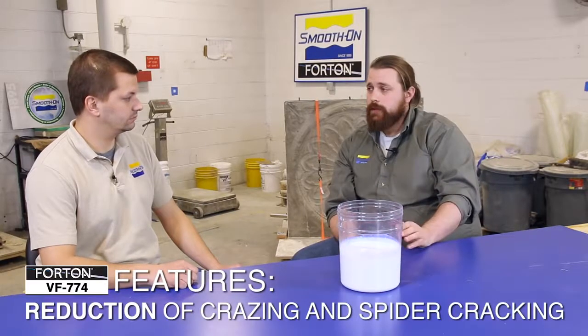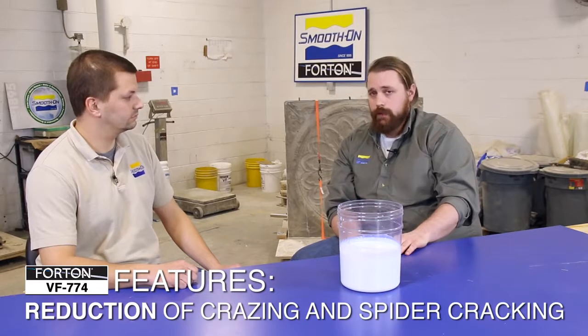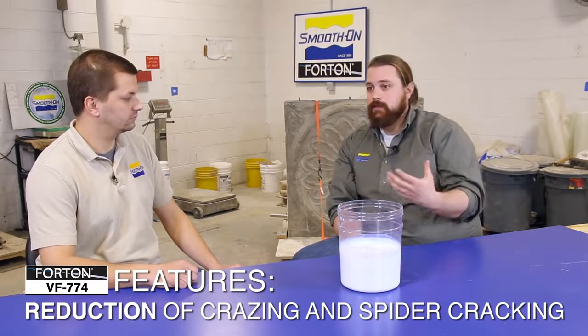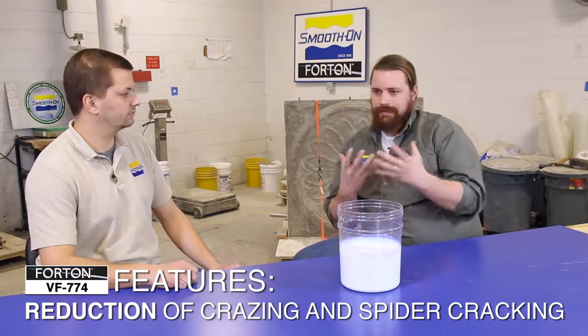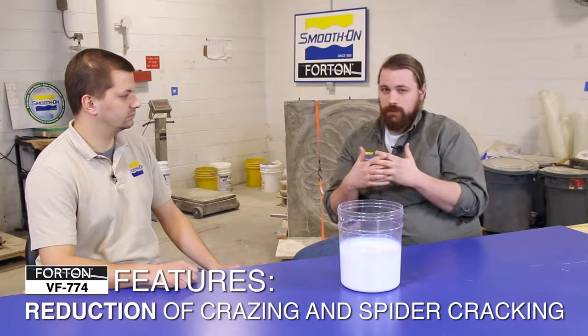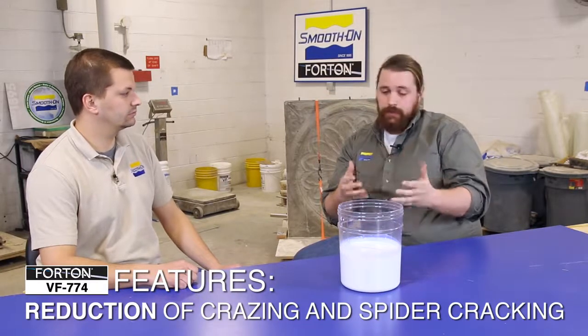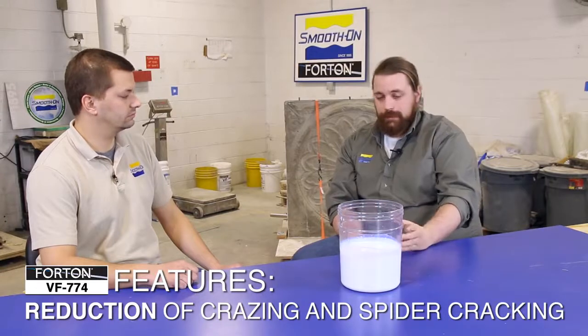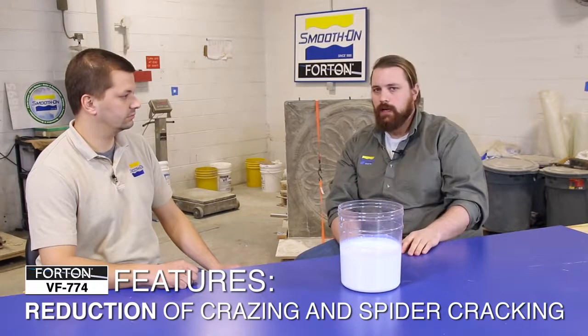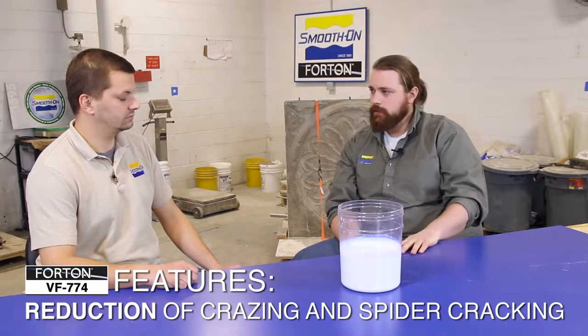Right. The other added benefit that you see a lot is a reduction in the spider cracking or craze cracking that can come about if you don't use any polymer. You'll see this at the surface of the part. As the concrete cures and shrinks a little bit, there can be some cracking. But with the soft polymer particles like this between the sand and cement particles, it helps reduce that spider cracking. So another kind of important factor there.